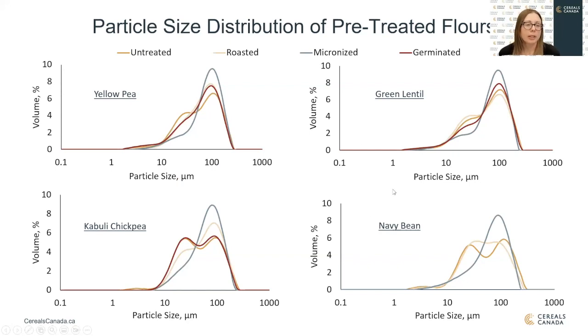Now looking at the particle size distribution of these flours, we saw that the micronized flours produced a narrower distribution, so a much more consistent particle size, where you can see that it's a single peak for the most part, whereas some of the other ones, like untreated and germinated, are more broad and maybe more bimodal.